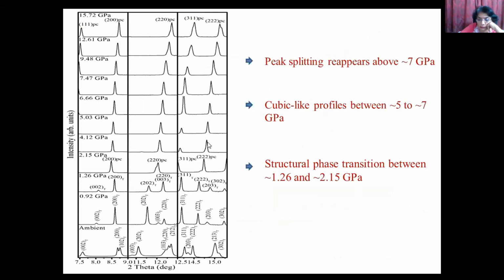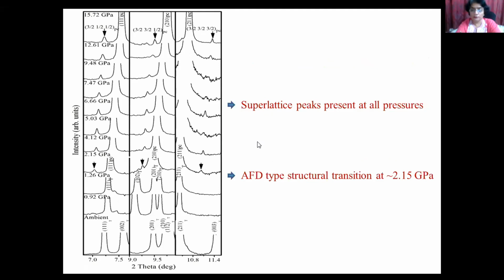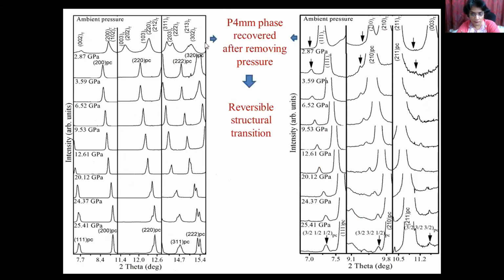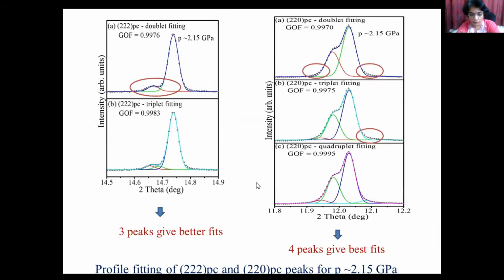Now between 5 to 7, there is an almost cubic-like singlet appearance, and above this pressure we can see that there is again splitting in this peak. The best feature was that at the same pressure, 2.15 gigapascal, we observed clear, nice superlattice reflections, which was direct evidence of an AFD phase transition. This P4mm phase was observed on decreasing pressure also, so it is a completely reversible structural phase transition. We analyzed the 220 and 222 peaks by peak deconvolution, which supports that it is not rhombohedral, because for rhombohedral, 222 and 220 should be doublets, but they were found to be triplets and quadruplets.